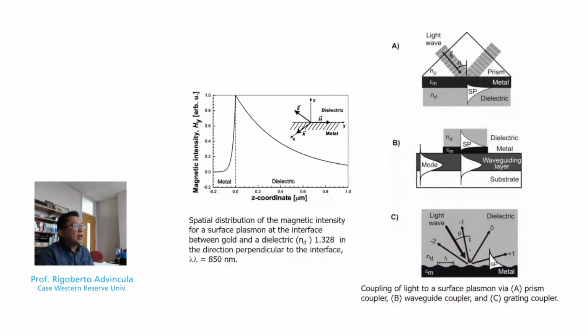So with this dielectric relationship, a gold surface in a dielectric media with about 1.33 refractive index shows that the intensity varies with distance, and the direction of this decay is perpendicular to the interface, let's say specifically at a wavelength of 850 nanometers.